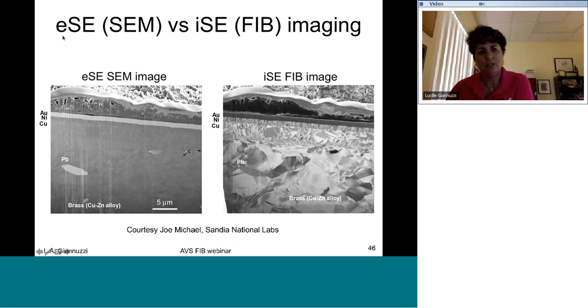The electron-induced secondary electron imaging versus the ion-induced secondary electron imaging is very different. You have to be careful with the interpretation. So here in the electron-induced secondary image, you tend to have your heavier elements brighter, your lighter elements darker, and this is somewhat reversed in the ion-induced secondary electron image.